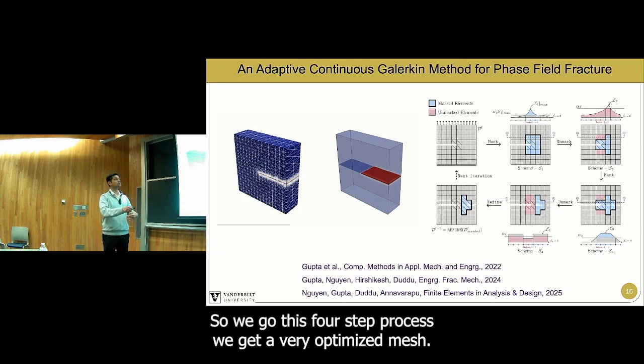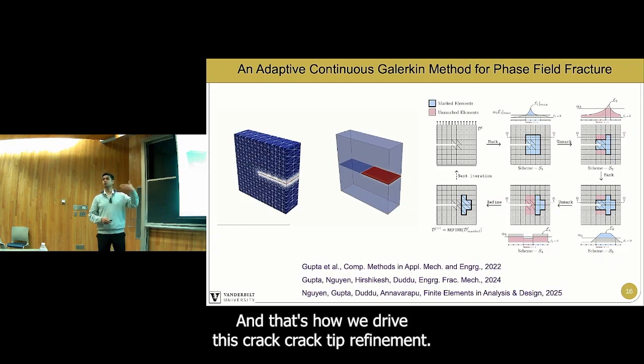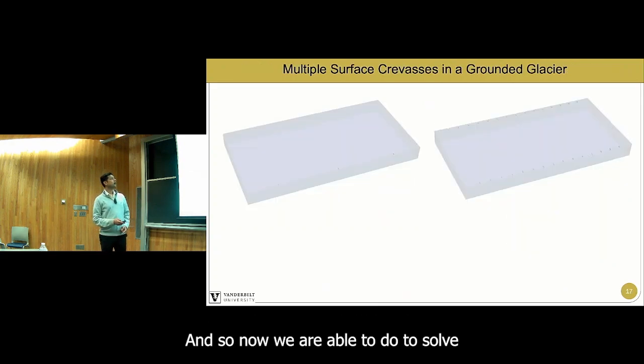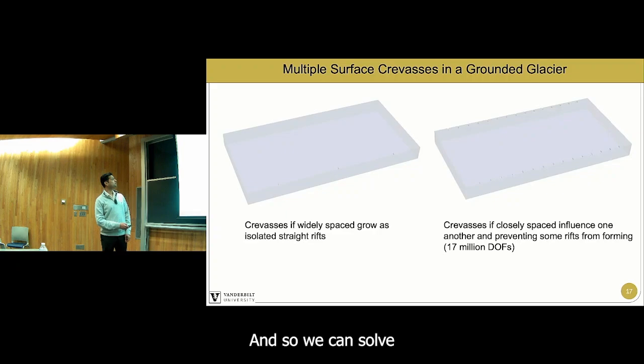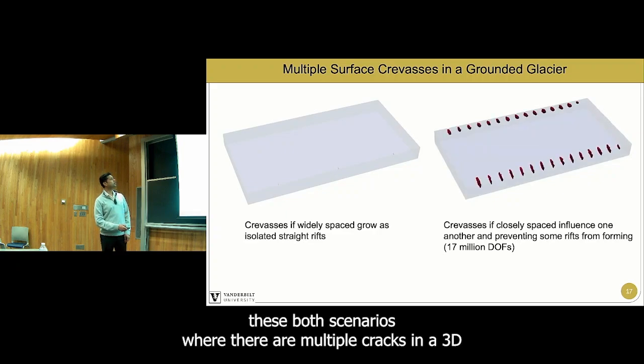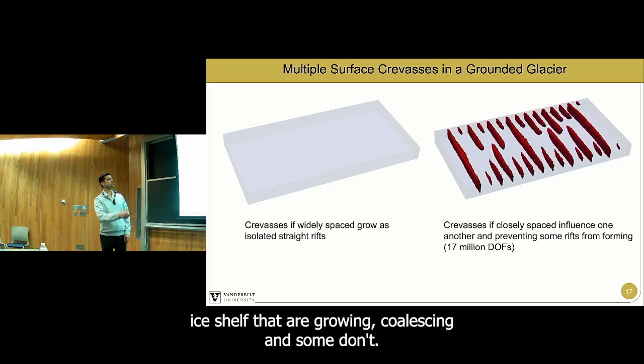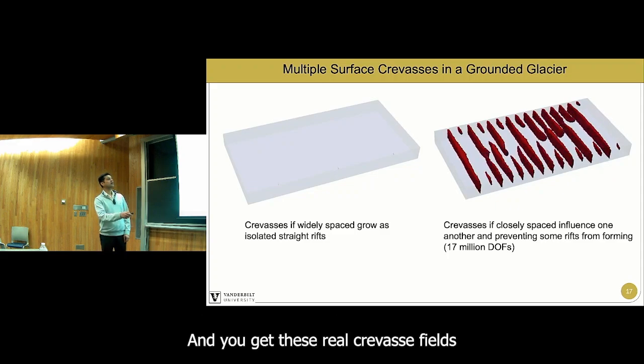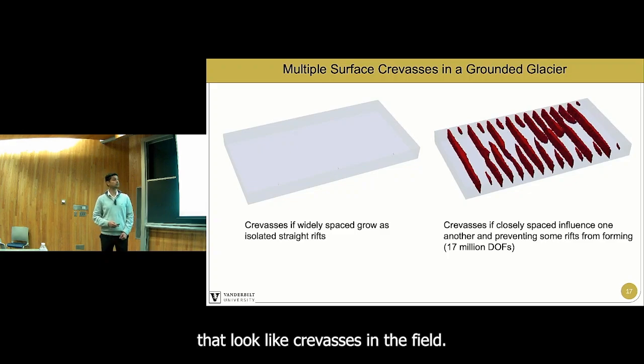So we go through this 4-step process, we get a very optimized mesh, and that's how we drive this crack tip refinement. And so now we are able to solve real crevasse problems in 3D, and we can solve both scenarios where there are multiple cracks in a 3D ice shelf that are growing, coalescing, and some don't. And you get these real crevasse fields that look like crevasses in the field.